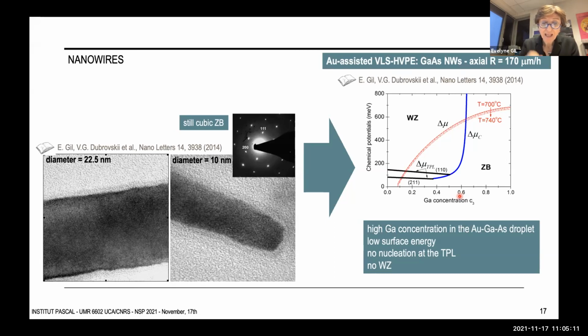So the high growth rates in HVPE come because we send high input of materials, high gallium input. So the consequence is that the droplets are gallium rich. We have a high concentration of gallium in the droplets. Then the high gallium supersaturation in the droplet decreases the surface energy. That suppresses the TPL nucleation, and no wurtzite phase can be observed, whatever the radius of the nanowire is.